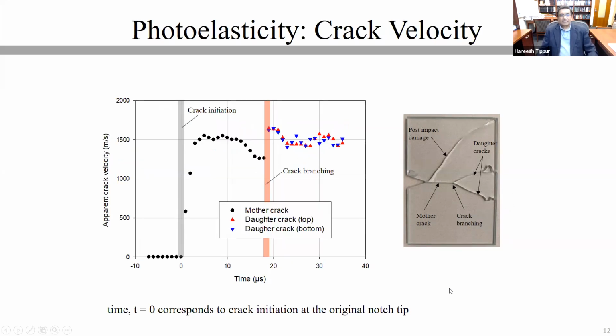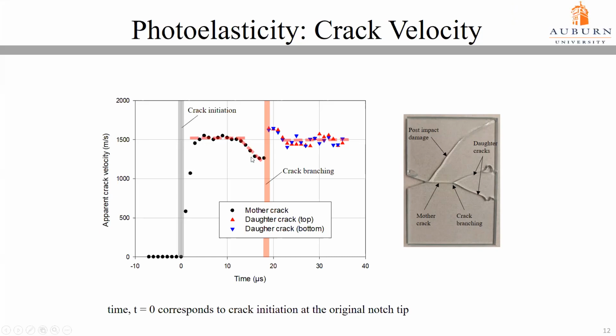You can measure crack velocities, and here is a plot of velocity as a function of time. And once again, the crack velocity jumps up. As I mentioned in the very early slide, this crack propagates very easily at 1,500 to 2,000 meters per second. And it reaches that speed within a matter of 2 or 3 microseconds. Then it is cruising along at this speed, and then it begins to slow down. The slowing down is a good indicator that something is about to happen.